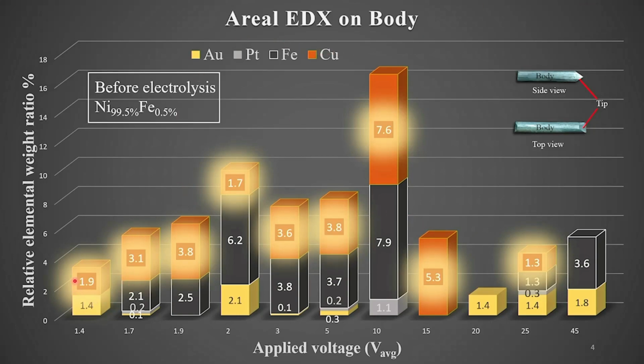Let's analyze this bar graph. These results are on the body area, which you can see in the figure. Here on the x-axis we have applied potential and on the y-axis we have relative weight ratio. For convenience, I have excluded the nickel weight ratio. Here, the orange bar refers to the copper weight ratio, yellow bars refer to the gold weight ratio, the grey bar refers to the platinum weight ratio, and the white bar refers to the iron weight ratio.